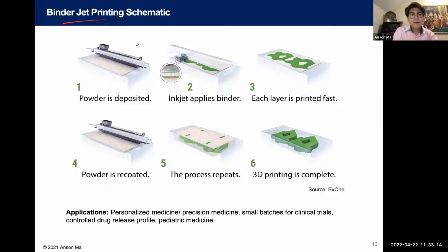Anyway, what binder jet is, let's say you have some powder material, you first spread a layer of powder, and then you use inkjet to jet a liquid binder. Once the binder reaches the powder, it's going to penetrate and wick into the powder bed, and it's going to spread both laterally and also penetrate. So let's say you put down a particular pattern, right? Powder, inkjet the binder to glue the powder together, and then you move the build plate down. So you move the platform down, and then you coat another layer of powder on top.